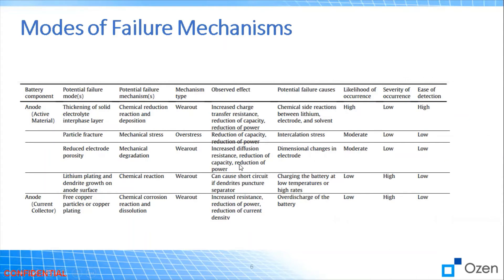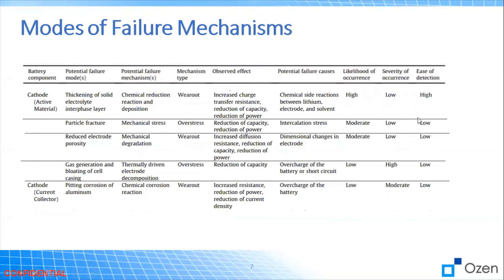Similar failure modes happen on the cathode, especially for the active component. At the cathode current collector, which is the aluminum part, there is pitting corrosion of aluminum due to chemical corrosion reactions, which causes wear out and increases resistance, and reduces power and current. Another failure mode is gas generation and bloating of the cell casing, which can affect battery life and reduce capacity.